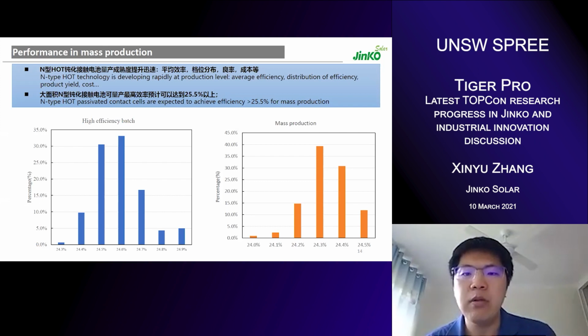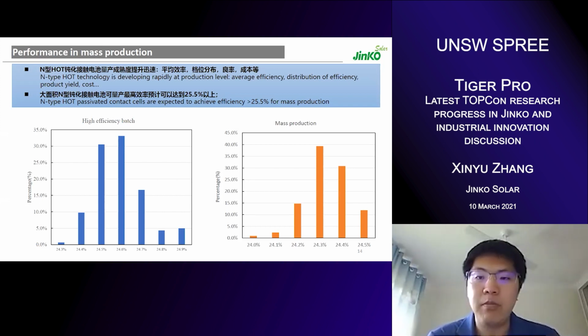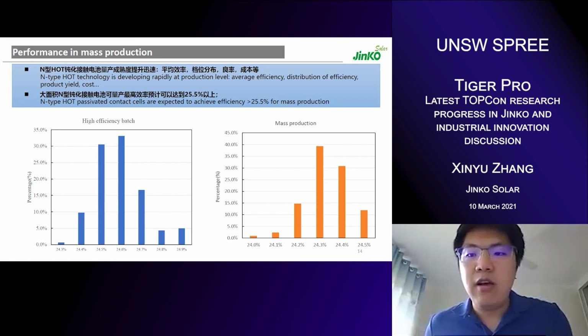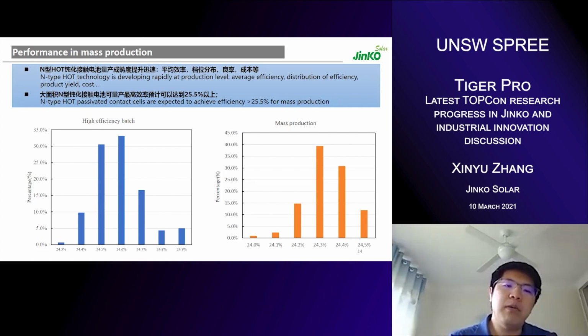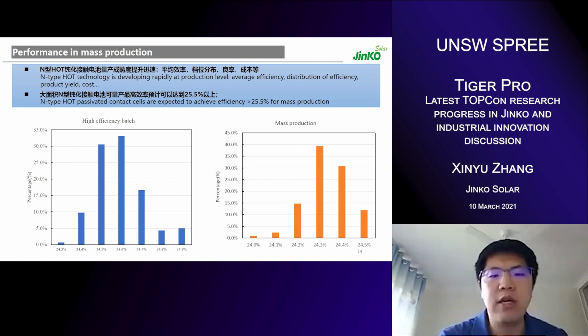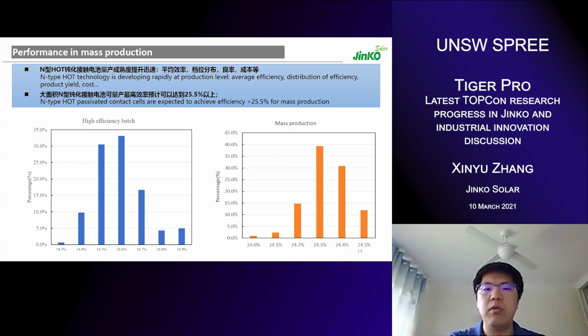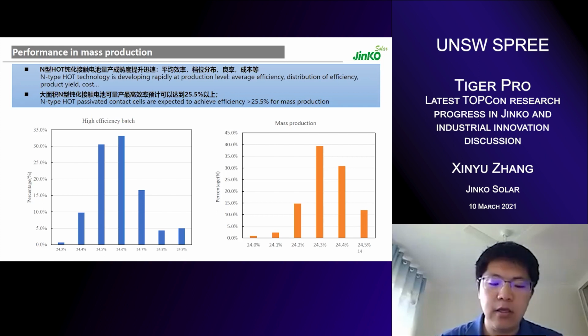I have to say that in terms of the production figures, the production operation people are doing a much better job than the R&D people, so the figures look very beautiful. But for us, further improving the efficiency is quite important. Our midterm target will be to achieve more than 25%, which has been proven to be possible in theory. And we also know that the highest efficiency for N-type TOPCon is about 25.8. So for mass production, it is the origin of the confidence.